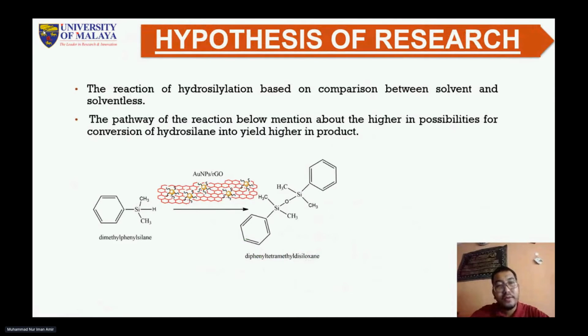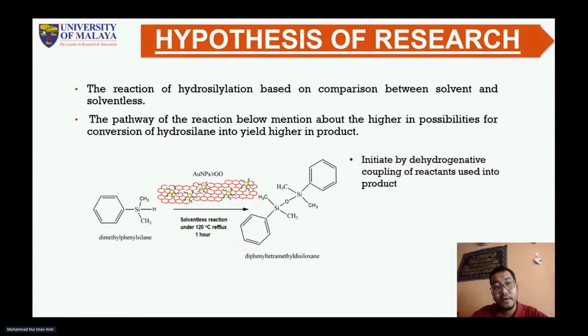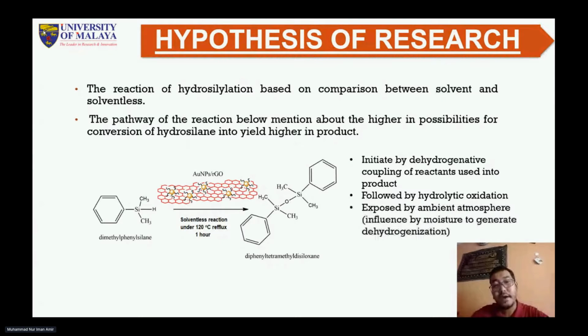We proceed to the hypothesis of the research. This is our proposed mechanism of that reaction, starting with the use of the substrate dimethylphenylsilane. Then the hydrosilylation reaction undergoes these steps, and lastly we get the final product, tetramethyldiphenyldisiloxane. This is because it is initiated by the dehydrogenative coupling of the reactant into the product, followed by hydrolytic oxidation. We observe it is exposed to the ambient atmosphere, under the influence of moisture, to generate dehydrogenation.